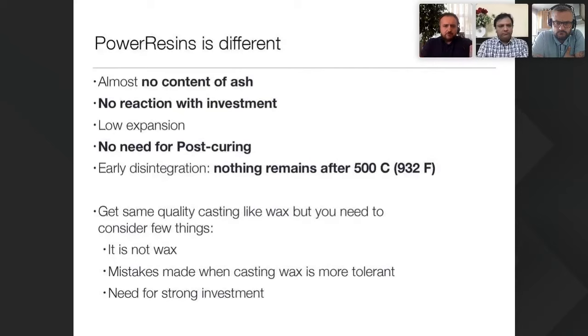So let's see what happens if you use one of our castable resins. You have almost no content of ash. In some of them you have a little bit of ash, but not so much - let's say 0.5, 0.3%, or a very little amount. That little bit is already removed during the burnout, because there is a sublimation process, which means the pressure, when it goes from solid to gas, removes that ash from the investment. You don't have any reaction with the investment.